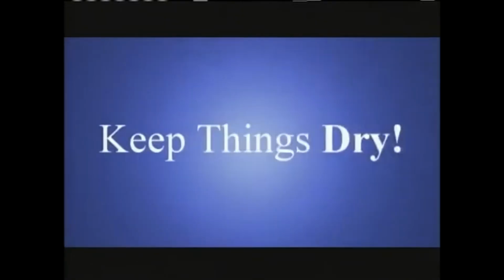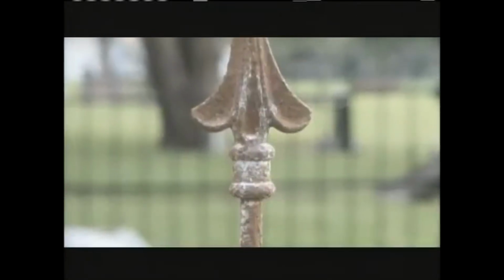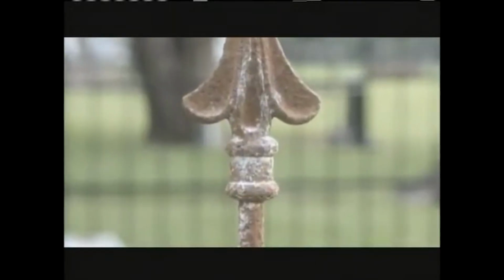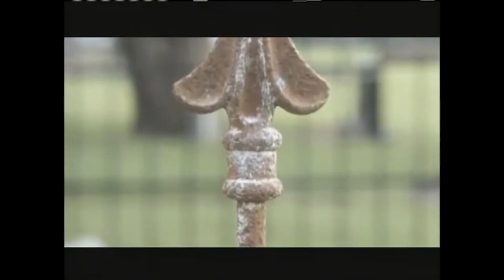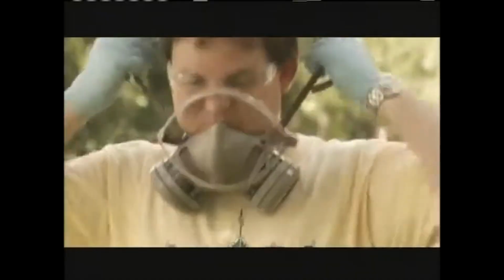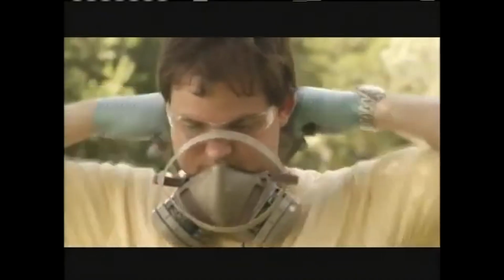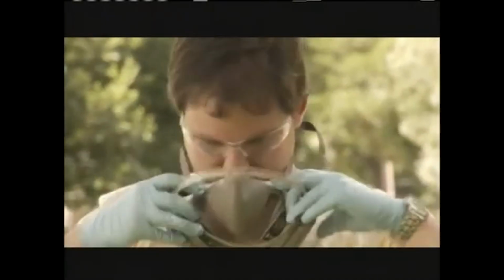is that moisture, including high humidity, cannot come in contact with the surface until the treatment is completely cured. If affected by moisture, the surface will turn a chalky white and must be re-cleaned. Keep in mind that when using any chemical, to follow the manufacturer's recommendations for safety and personal protective equipment.